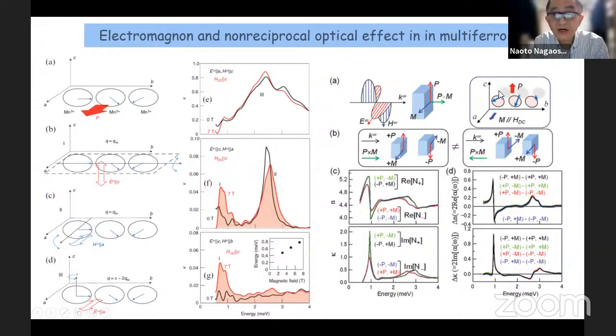But actually, in the case of this conical structure, the uniform magnetization and the polarization coexist, then this P cross M roughly corresponds to the vector potential for the light. So this directional dichroism occurs for these multiferroic materials with both P and M. So depending on the direction of the propagation of light, the absorption differs like that. So this electromagnon excitation is a very hot topic in the field of insulating multiferroics.